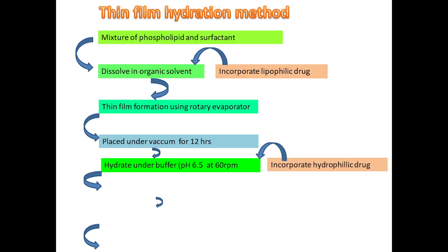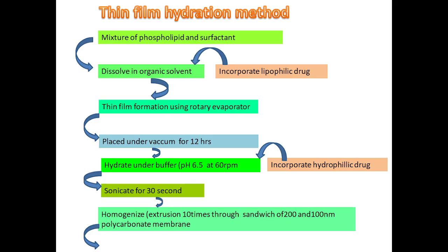Here the hydrophilic drug is incorporated. Then sonicate for 30 seconds. Homogenize. Extrusion 10 times through a sandwich of 200 and 100 nanometer polycarbonate membrane.